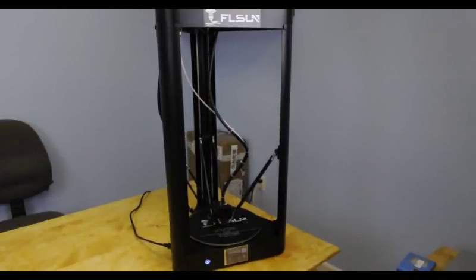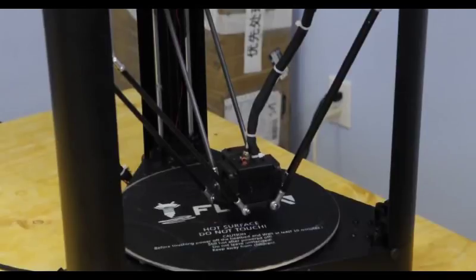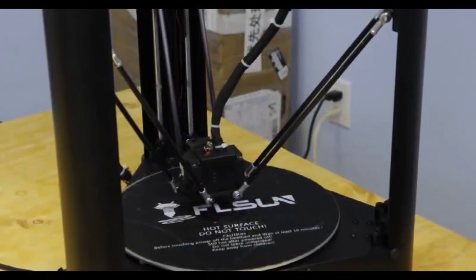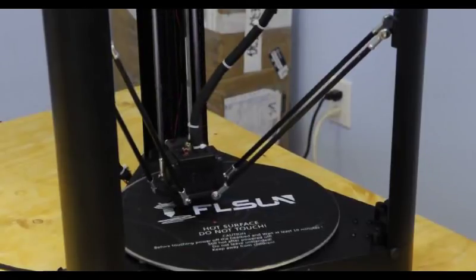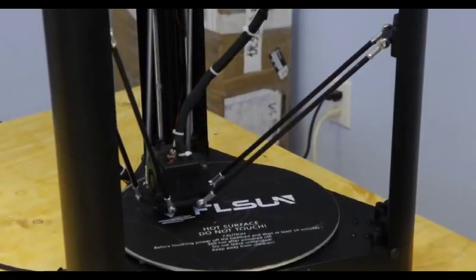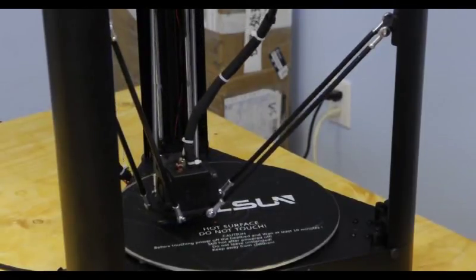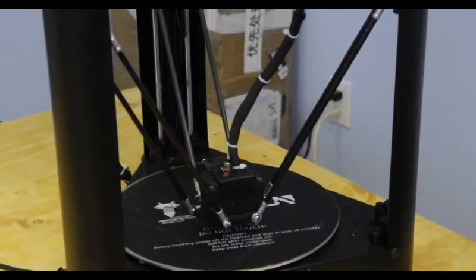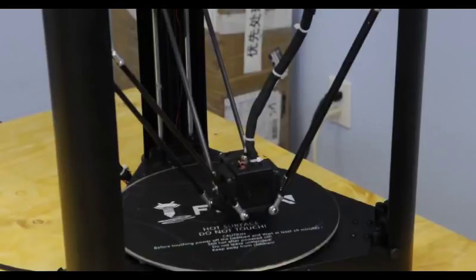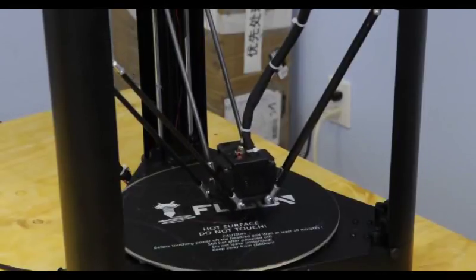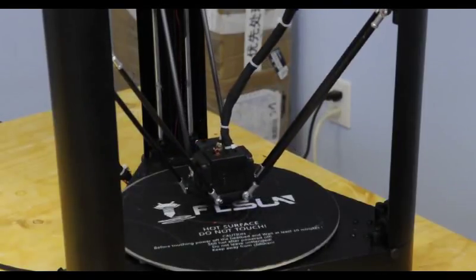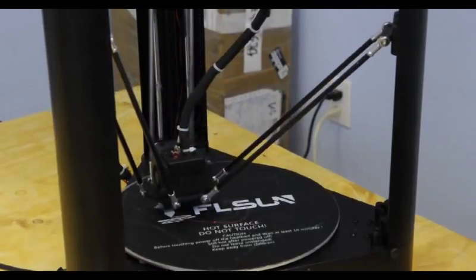I decided to use the wireframe skull as my model in doing the flexible filament test. I wanted to test the full capabilities of the printer utilizing this difficult material. Printing with flexible filament requires a somewhat different mindset than standard filament. You want to maintain a steady flow of material through the nozzle so as to avoid any excessive back pressure which would cause the material to kink in the Bowden tube or in the extruder.